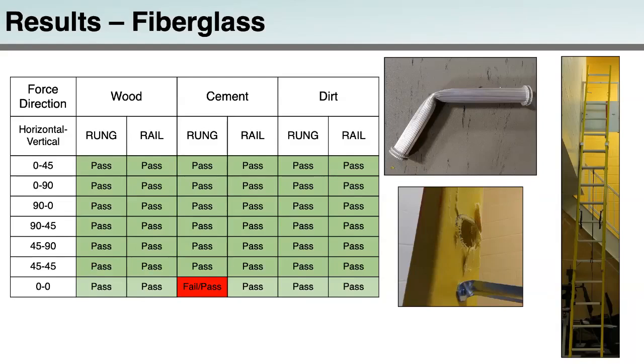This failed upon initial testing, but passed when we retested the condition. And this was actually the first of the 0-0 drop conditions for this ladder. So during the failed test, the rung deformed upon the load drop and the adjacent rails underwent some slight fracture. So you can see here that this is the end result of what the fiberglass ladder looked like after that failed drop. And this is the rung that the tether was wrapped around.